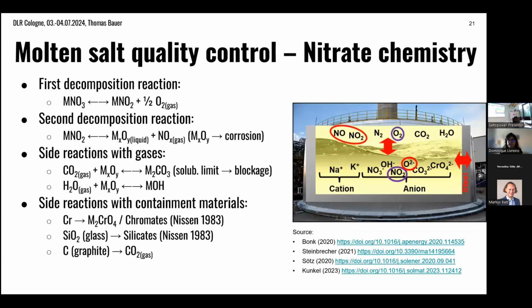So coming to the molten salt chemistry or the nitrate chemistry, we have the cations and the anions, the nitrate and nitrite, and then we have different reactions. The two important reactions: the nitrate can decompose to the nitrite and releases oxygen. The oxygen is dissolved at low level, and then it will evolve from the salt. We even saw it if you heat up solar salt. You watch it, you can see bubbles and the oxygen arising. There can be also quite a lot of oxygen coming out of your system in the first instance, because this reaction needs to come into equilibrium, especially at high temperature first. And then there's a second decomposition reaction where typically it's said that the nitrite decomposes to oxides.